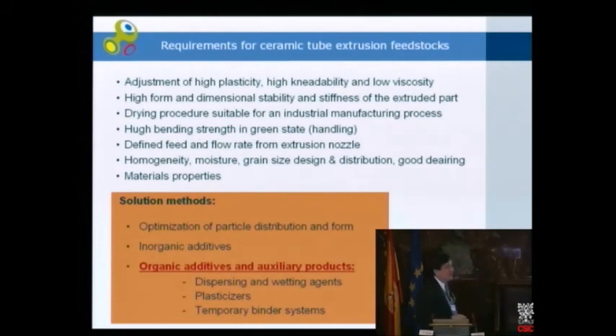And you all know silicon carbide has absolutely no plasticity that can be exploited for forming and shaping. And we can hardly use a distinct amount of inorganic additives. That means all the plasticity, all the rheological behavior, and that means also the strength and the handling safety in green state must be performed by a set of optimized organic additives, binders, plasticizers, and further auxiliary products like dispersing and wetting agents. The most important are the temporary binder systems. Temporary with respect to the thermal treatment, to the sintering, or to the reaction bonding.